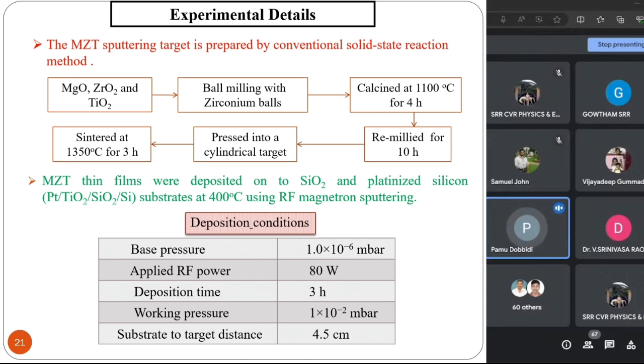But suppose if I make 200 nanometers, that means 1/5 of the thickness of your hair. The thickness of your hair is about a micron, but we are making a thin film which is 1/5 of it, about 200 nanometers. And when we make a 200 nanometer thin film, how does it behave? We want to see the material that we have prepared in bulk form, and when I make it as a 200 nanometer thin film, how does it behave? That is what we want to see. To do that, we made a target, and these are the deposition conditions, with the vacuum technology, all that.